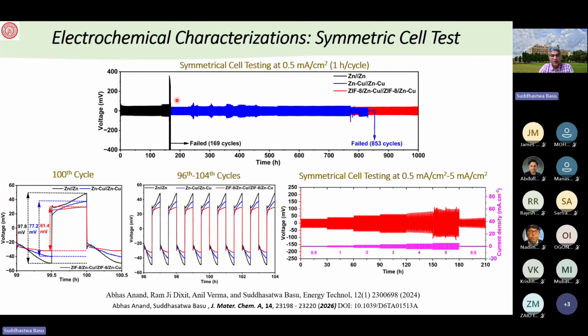First is a symmetric cell. You can see the red one is ZIF8 zinc copper, and it's still running till about 1,000 hours. And one can see that the blue one, the zinc copper cell, no MOF, runs up to about 853 cycles and then it ceases to operate. Same thing with no MOF or no ZIF8, only zinc, and this fails after 169 cycles. Here we are showing for the ZIF8 and between zinc and zinc copper, ZIF8 and zinc copper and zinc, how we have a lower polarization resistance and lower onset potential when you have the ZIF8 structure, as shown here, the overpotential.